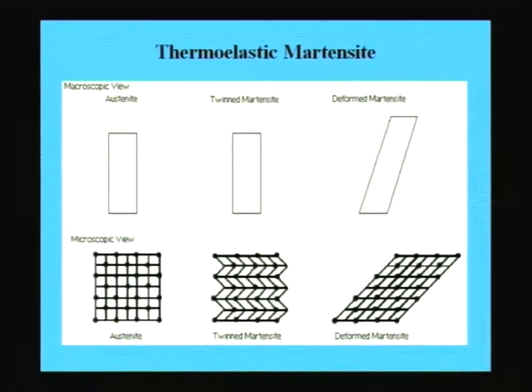Okay, what is this thermoelastic martensite? If you look at the austenite, in most of these things it is cubic in nature, the B2 type of structure. If the B2 transforms to the thermoelastic martensite, the strains that are present during this transformation are absorbed into this martensite in terms of a lot of twins. You get a lot of twinning inside the martensite where the strain is stored, and if you deform this martensite at temperatures below the MS temperature, the deformation leads to a shear type of deformation and deforms this martensite, and when you heat it back, you get back this particular structure.